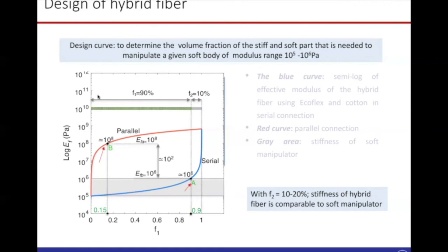Now for the stiff part, either you can use a completely cotton fiber, that's fine, or else you can also use a mixture of cotton and Ecoflex itself, but they should be connected in parallel. So here we adopted that method, and the parallel connection curve is given by the red curve. We reinforce Ecoflex with a cotton cross-sectional area of around 50%. So just by using 50%, you can see you can make a highly stiff part. So now by locking or unlocking, you should get an approximate difference of around 100 times if you choose F2 equal to 10%.